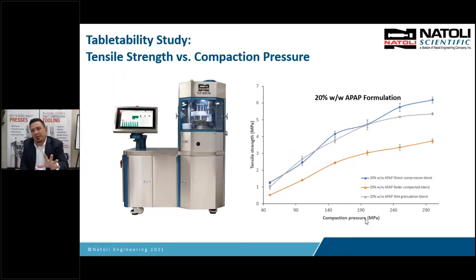Okay, so again, tensile between 1 and 2 megapascal. Now, if you want an ODT, an orally disintegrating tablet, it needs to disintegrate in less than 30 seconds, there's certain materials you add in that are super disintegrants. But in those particular products, your tensile strength might be at 1, maybe a little lower than 1 megapascal. So depending on your product and how fast you want the disintegration properties, that'll determine your tensile strength.